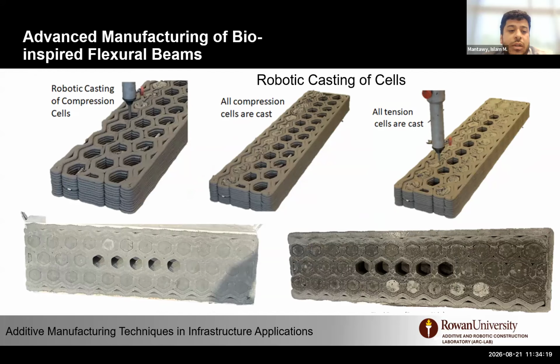The caveat here actually is that once we print and cast close to the time, we were surprised that they fuse really nicely. There are no cold joints. I actually have one sample here with me that can show you clearly the material was fused nicely. And for the 5 cells you can see here, just because of the geometry, we have limited benefit of optimization, but in larger elements, you can see the benefits.